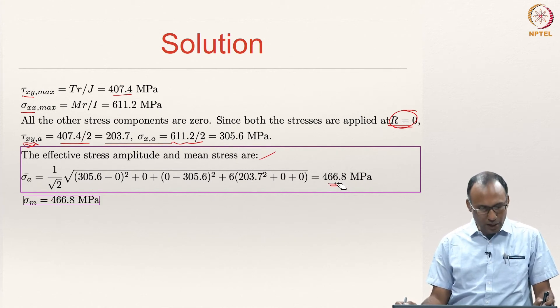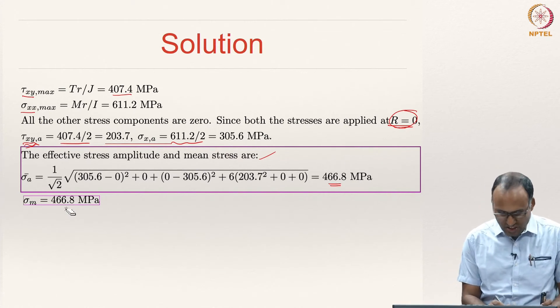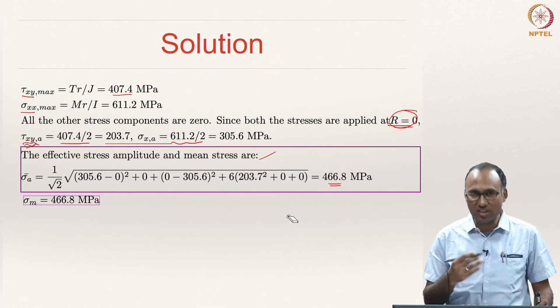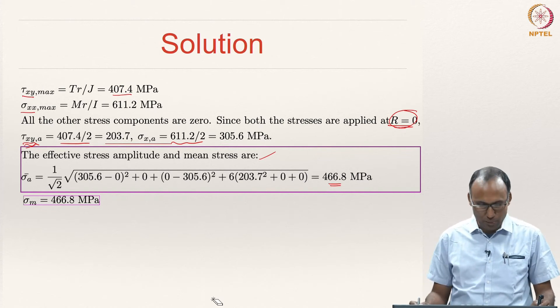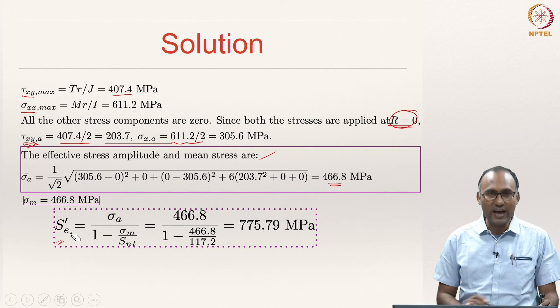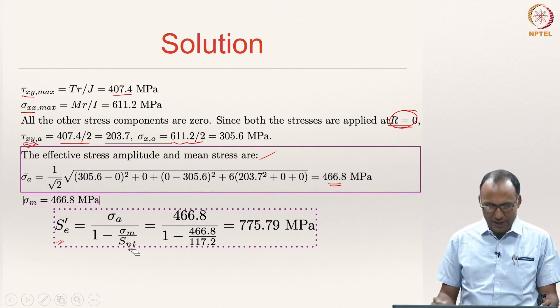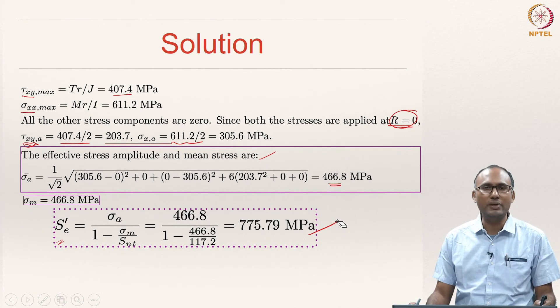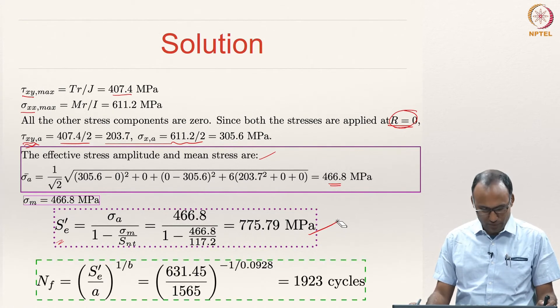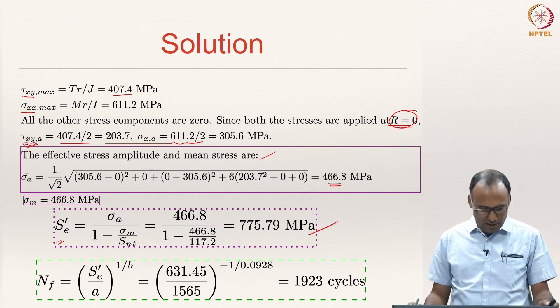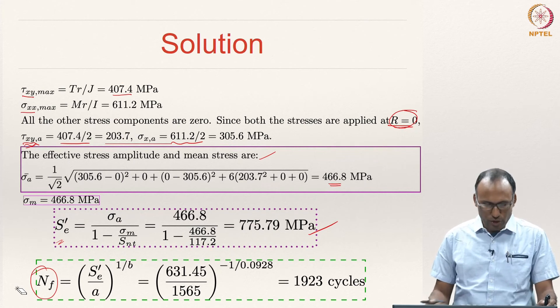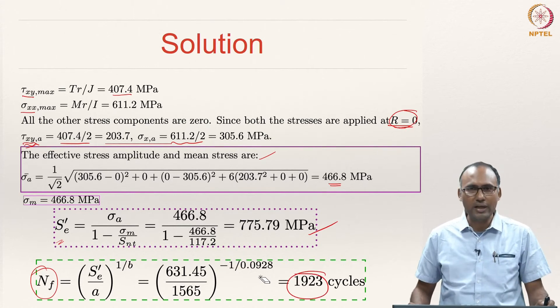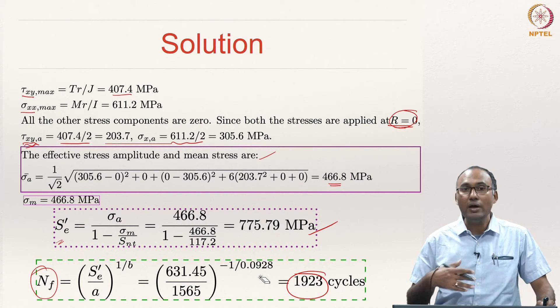Then you calculate the effective stress amplitude using the von Mises stress formula from the normal stresses and shear stresses, which comes out to be 466.8 MPa. Since R = 0, when R = 0 the stress amplitude and mean stress are equal — as already discussed when talking about types of fatigue loading. Then you plug that into Se' = sigma a / (1 - sigma m / Sut), and calculate Se' = 775.79 MPa as the uncorrected endurance strength. Corresponding to that, the number of cycles to failure using Se' = A·N^b gives 1923 cycles for this combined state of stress.